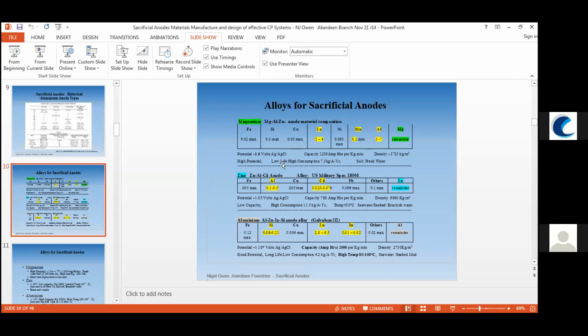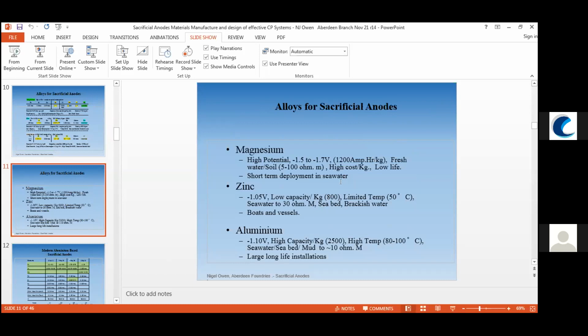But we have different properties for these three, and I think it's summarized a little easier in here, whereby magnesium anodes are of a high potential and they're fairly reactive, particularly if you try and put them in salt water. So they're limited to use in, say, fresh water, and they're extremely useful for burying in soil where you've got clays and bentonite, etc., which gives you a conductive medium. You can also use them in short-term deployment in seawater, but they do fizz like sherbet. They're also used for cleaning tanks, whereby it blows the descale and the paint off the inside of tanks. That's just an alternative use.